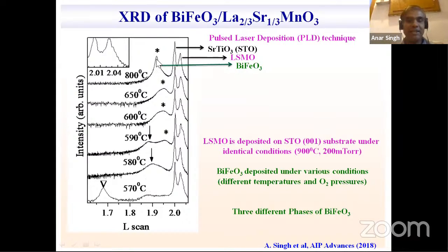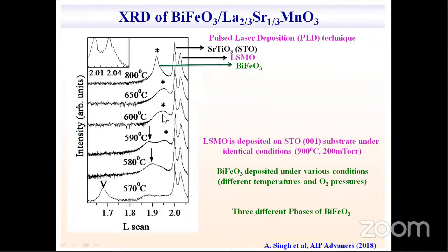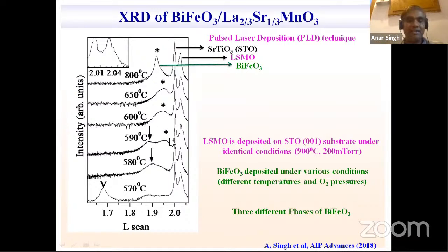And we can see here that with decreasing deposition temperature, there is a change in the X-ray diffraction pattern. Some new peaks appear at lower L values, and finally at 570 degrees centigrade, we have a